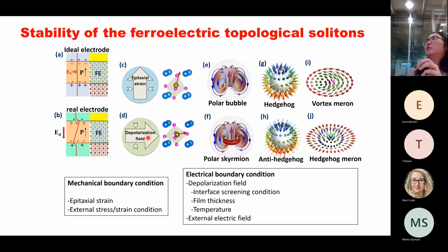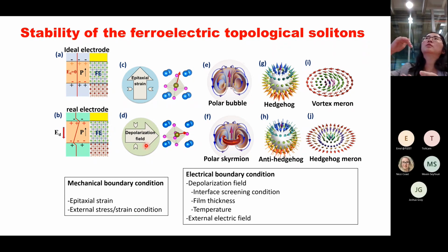So at some point, to minimize the effect of the depolarization field energies, it will try to form these 180° domains. But at a critical point, it will push too hard and form in-plane polarizations. So this will form the polarization curling. All these curlings are a result of the epitaxial strain stabilized on the outer plane and the depolarization, which is trying to reduce it.